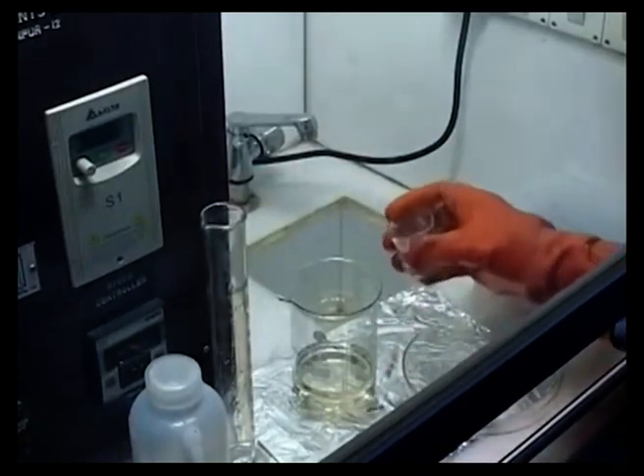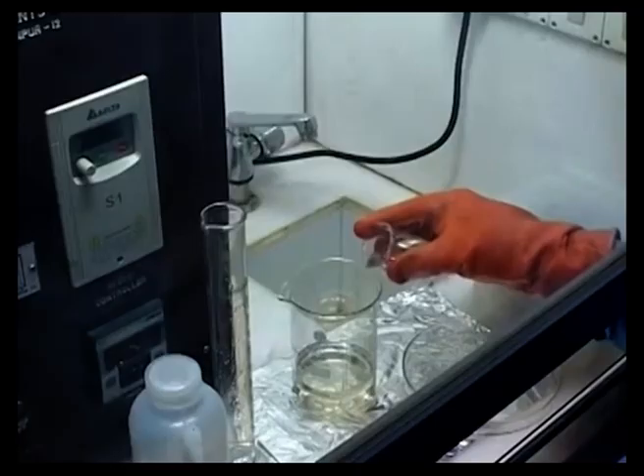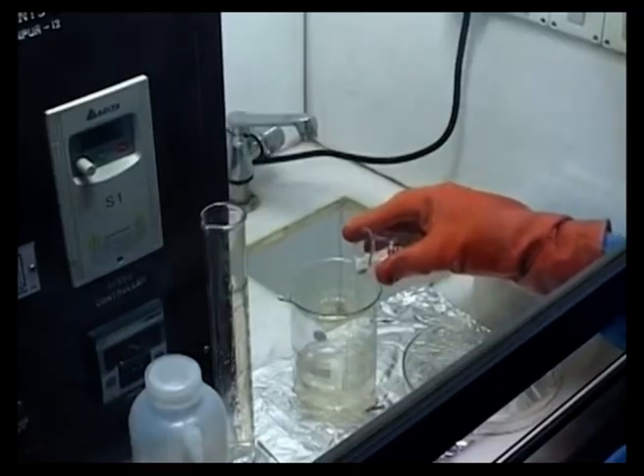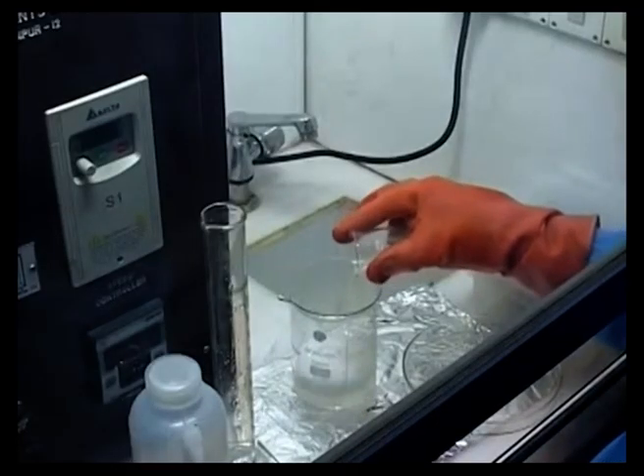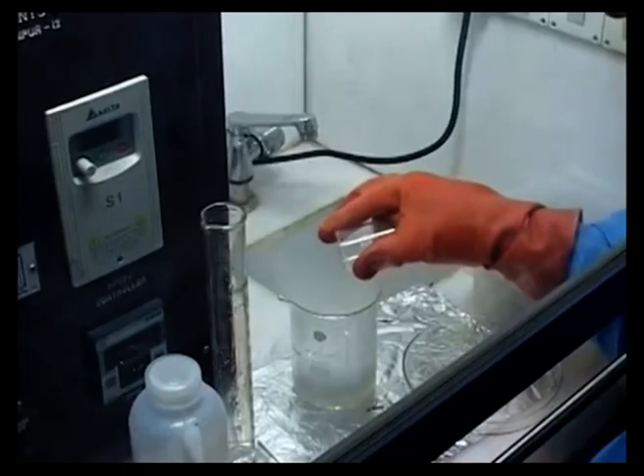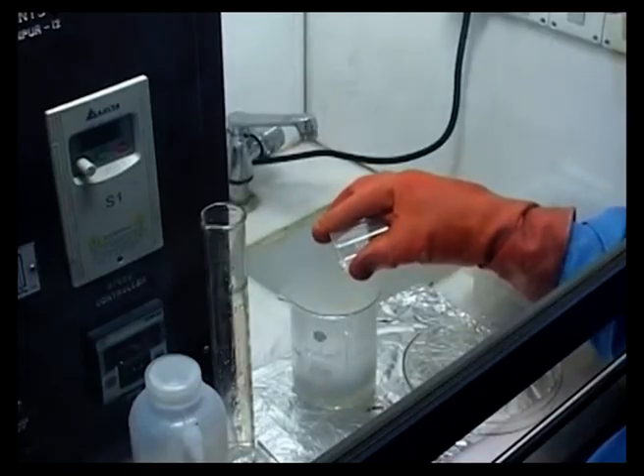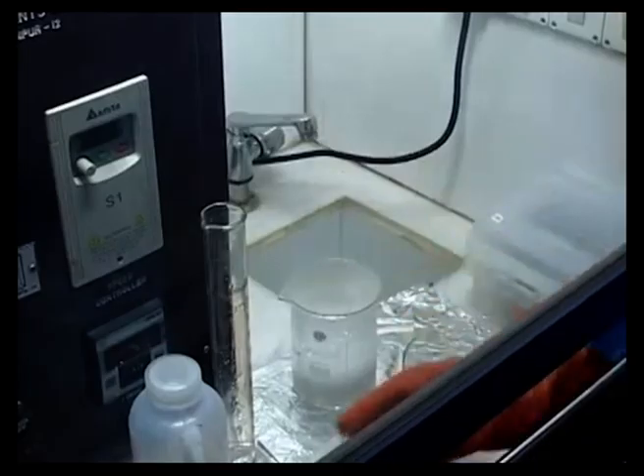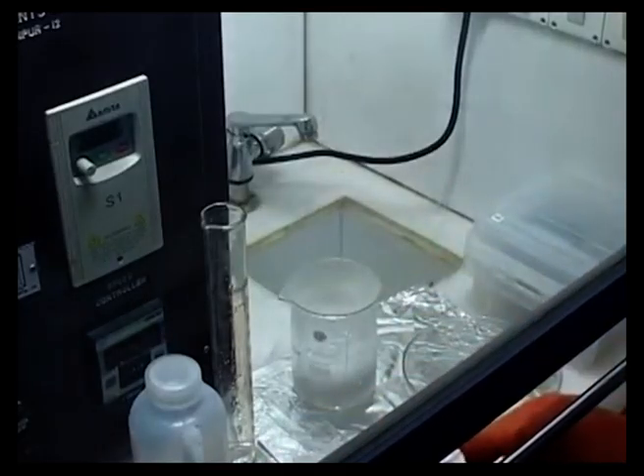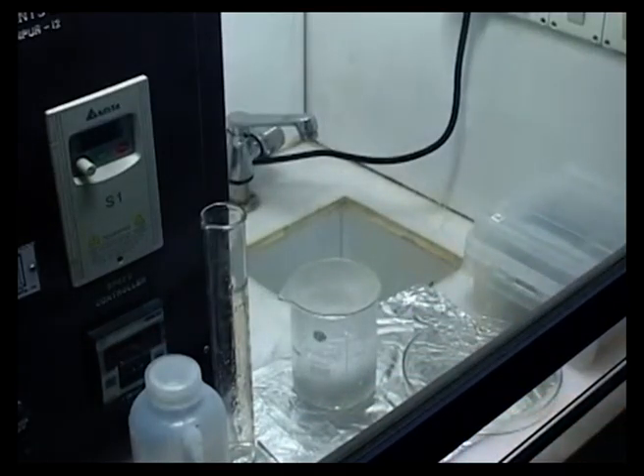So as you see, when you pour the material, there is immediate reaction which takes place, and there is a lot of fumes which are generated, as you can see, and this has to be done in a very, very closed environment, and we have to wait for some time till this fume actually disintegrates or disappears totally, and piranha is made in that process.